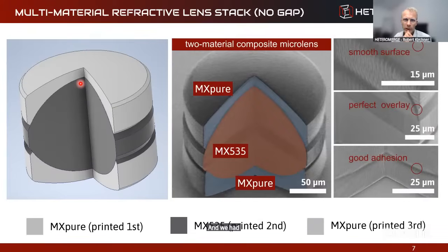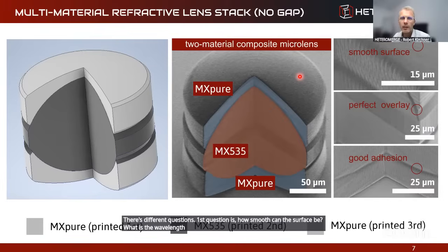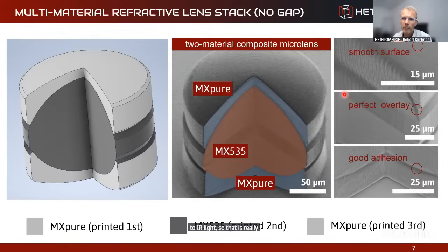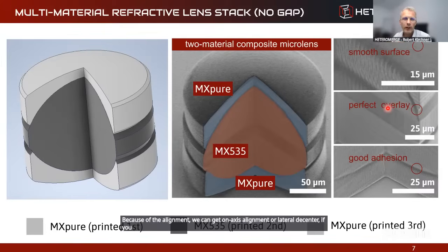And we had this before, so of course, there are different questions. First question is, how smooth can the surface be? What is the wavelength range that is applicable? So the surface can be down to below 10 nanometer surface roughness. So you're addressing visible light to IR light. So that is really attractive. Because of the alignment, we can get on-axis alignment or lateral decenter, if you wish, below 50 nanometer in any case. So it will be a 3 sigma value. In most cases, 1 sigma would be below 25 nanometers.